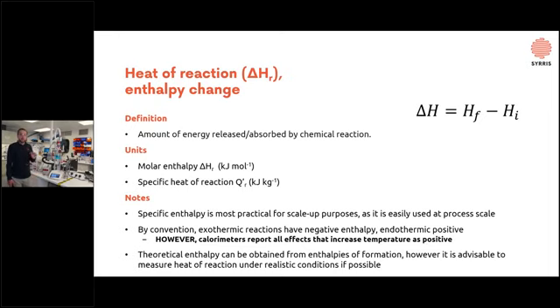There is one quirk with most reaction calorimeters though, because as I guess quite a few know from thermodynamics, endothermic reactions have a positive sign and exothermic have a negative sign. Most commercially available calorimeters will report it the other way around, which is a bit counterintuitive. But it actually makes sense in a way, because calorimeters report all effects that lead to a temperature increase, meaning exothermic effects, as positive. And we can calculate the enthalpy change quite easily, theoretically, from enthalpies of formation if we know our process really well. However, it is always advisable to measure the heat of reaction under realistic conditions to confirm the calculations.